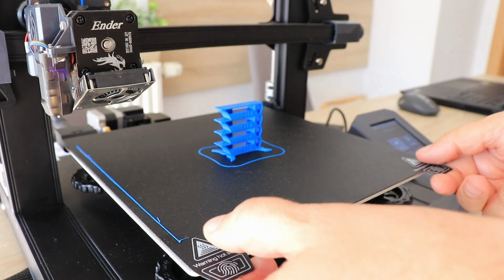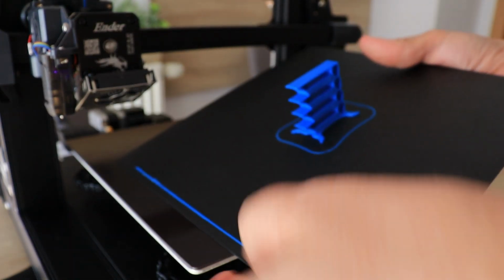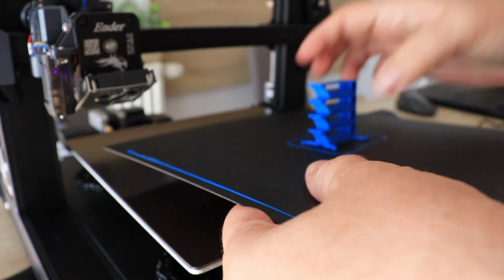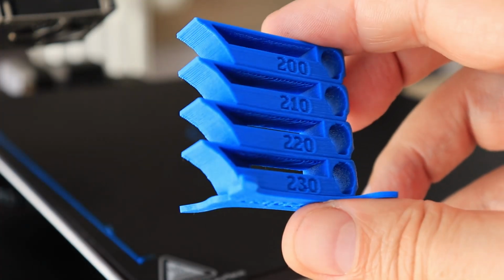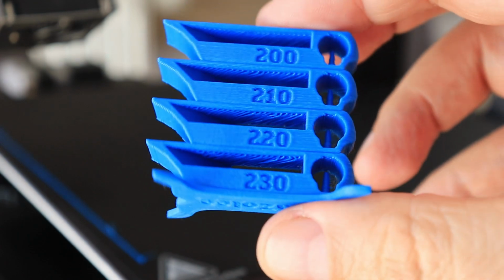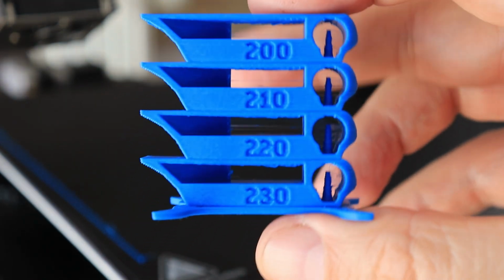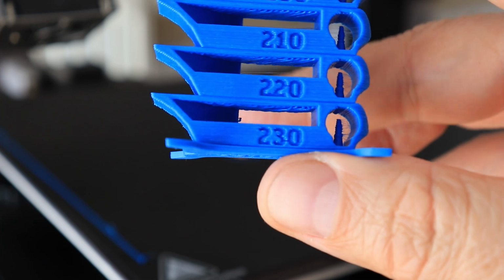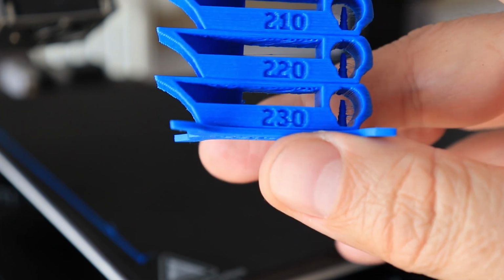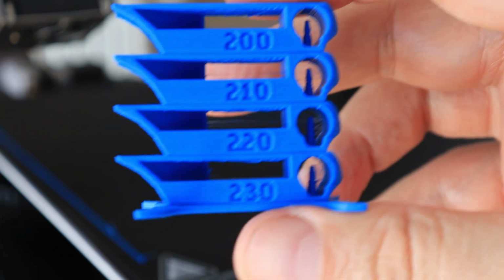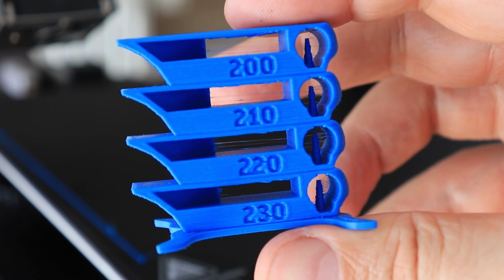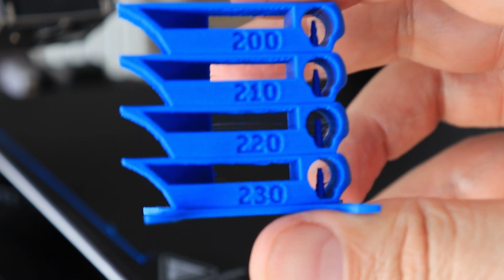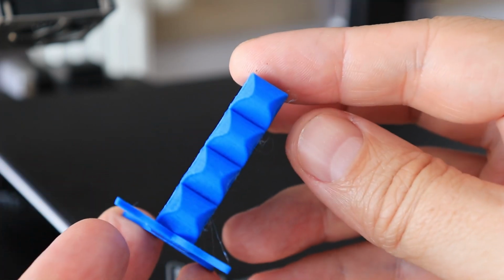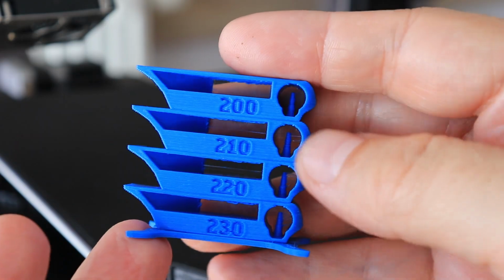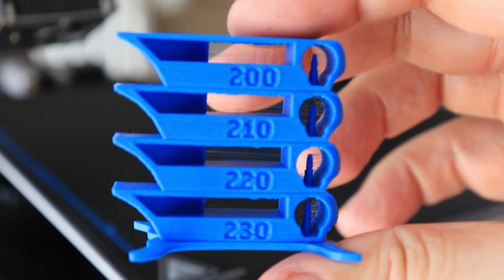Printing is finished, let's remove the object. And actually this printing looks great, perfect overhang, and the bridging, only I can see a little bit more stringing than I usually see on the PLA. But if this will be the biggest problem, I don't mind, because this material has great specifications according to the website. So I think I will print all test specimens on open printer, and as I mentioned earlier, only the layer adhesion test will be reprinted inside the enclosure too.